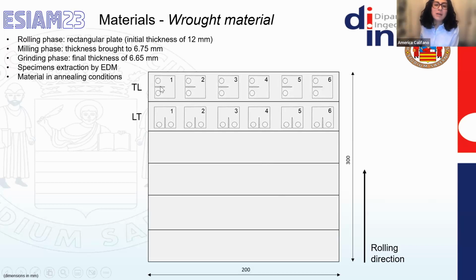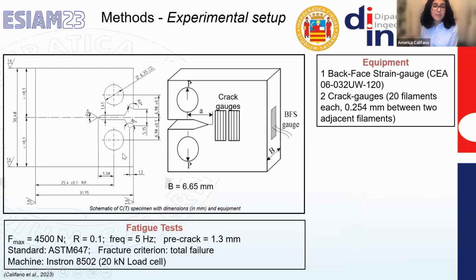The specimens are identified with 2 letters and a number. The 2 letters stand for the direction of the notch. So if the notch is orthogonal to the rolling direction that is shown here in the slide, the designation is TL followed by a number. Otherwise, if the notch and therefore the crack is parallel to the rolling direction, the designation is LT followed by a number. In this contribution, I will show you the results for specimens TL 1 and 2 and LT 1 and 2 that have been subjected to fatigue tests.